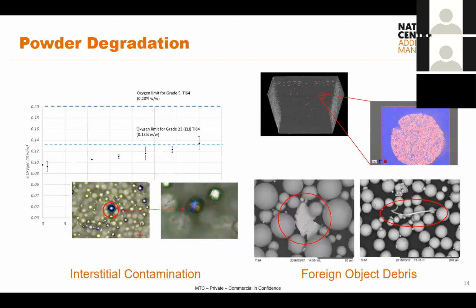And so when we look at powder degradation, some of the things that I think we need to be most concerned about, I think there's two of them. So the first one is interstitial contamination. So the graph shown on the slide on the left as you look at the screen shows real, again, it's fully anonymized, but real data captured at the MTC, showing a titanium powder, which initially is within the ELI grade. So that's the extra low interstitial grade for titanium 6-4. So spec limit of